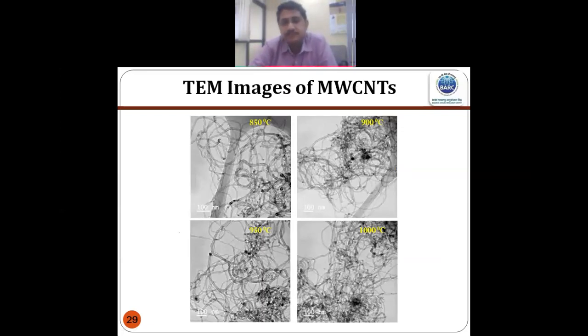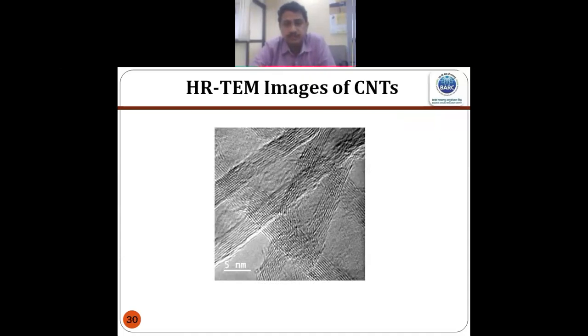These are typical TEM images of the carbon nanotubes which we produced at different temperatures. This is the high resolution TEM, where we can really find the number of layers. So you can find from 8 to 13 layers of carbon nanotube.